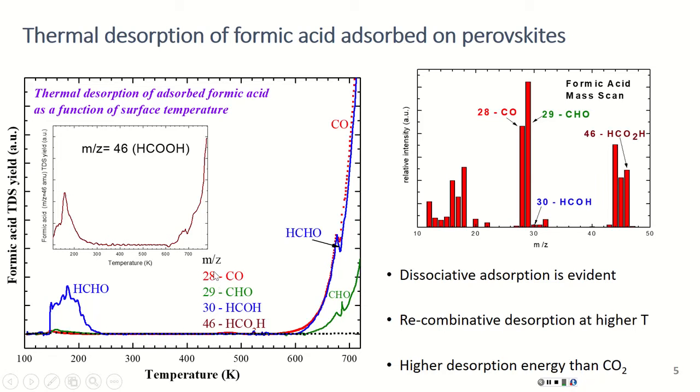So that means the formic acid desorbed dissociatively during this thermal ramp. The intensity of the molecular mass fragment of formic acid is relatively low at high temperature, but we can see a small amount of molecularly desorbing formic acid parent mass fragment, and this can be mainly due to associative desorption of the adsorbed formic acid.